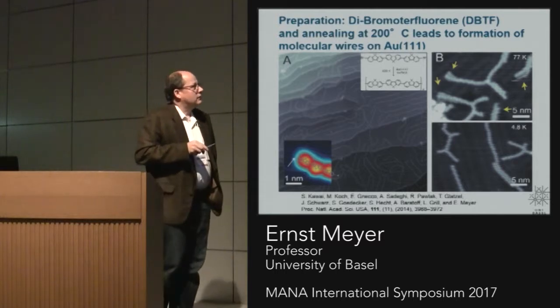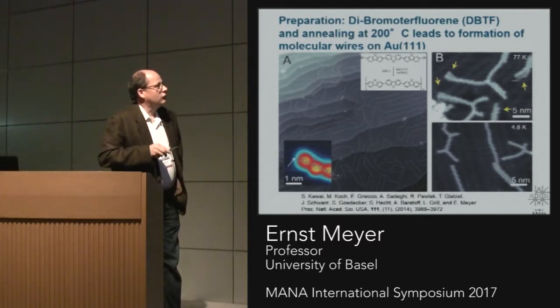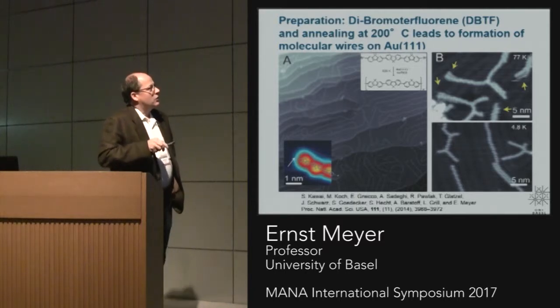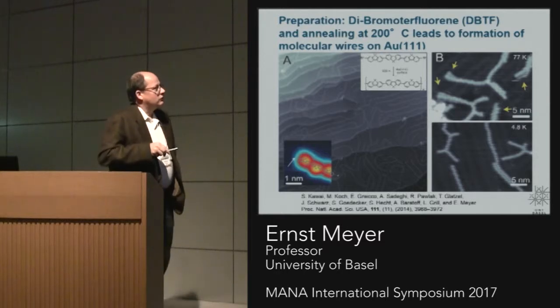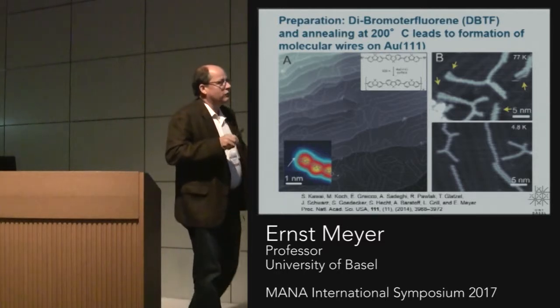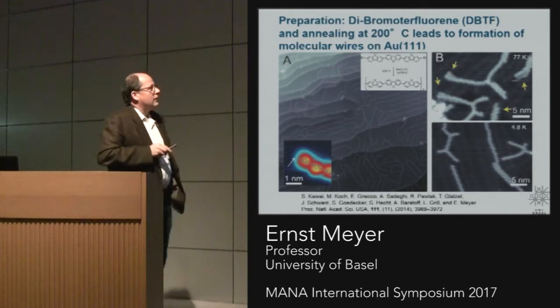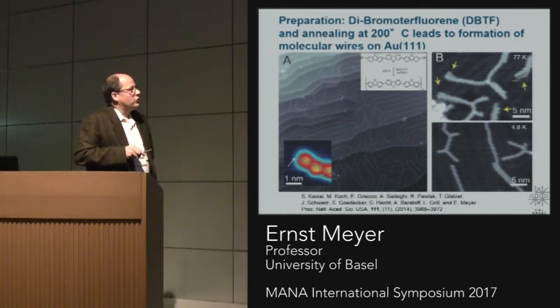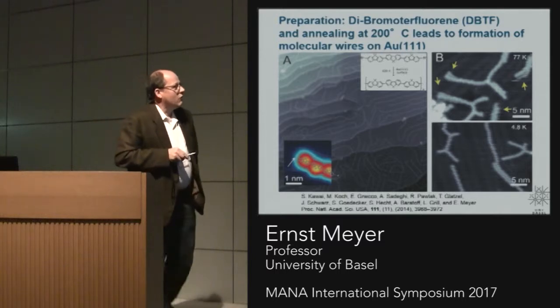Here in this case it was this dibromoterfluorene, so basically these 3 units here, and you have this bromine at the end. So you evaporate on the surface, then you heat to 200 degrees, and then the bromine will basically move away and it will form this polymer. So these little guys here, they are already these polymer wires.